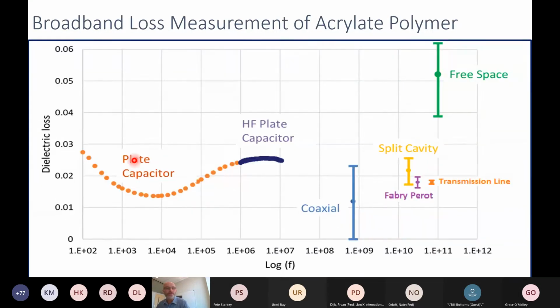In terms of the loss, here we can see our low frequency, and then we have a little bit higher frequency adapter for that, and we can start seeing this peak, which will come down, and then we get yet another increase as we go to the higher frequencies. Of course, this sort of material that's 3D printable probably is not going to be used for a lot of 5G applications, but as I mentioned, it's very useful because we can make a variety of samples to compare and contrast all these different measurement techniques.